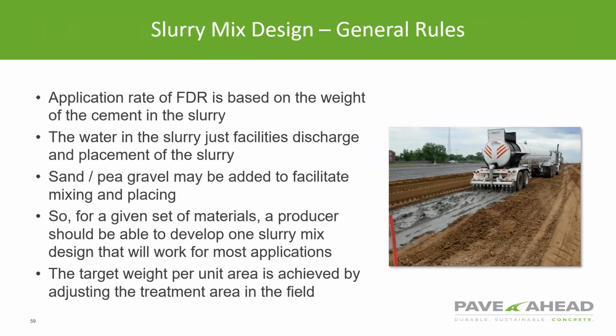As far as the slurries, once you get out on site, again, the application rate is based on the weight of the cement in the slurry, and the water is just in there to facilitate discharging. Sometimes sand and pea gravel may be added to facilitate the mixing and the placing of it, the flowability. So really, for a given set of materials, a producer should be able to develop one slurry mix design that works best for their materials.